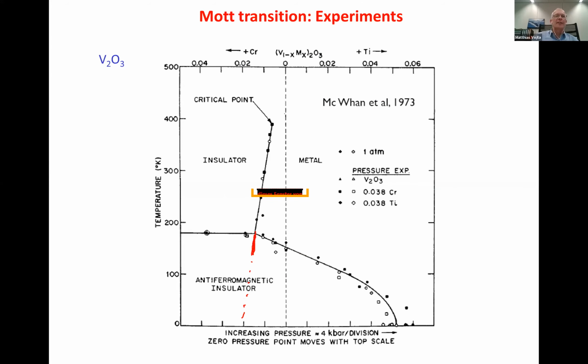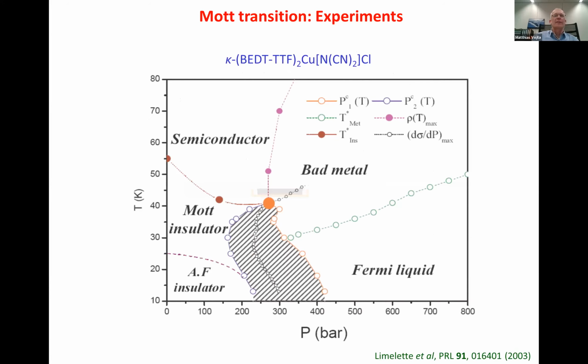Again, for the vanadium oxide, there must be a clear-cut experimental answer, but these data I'm showing are from the 70s, so I'm not sure whether this has been investigated in detail. In these phase diagrams, you actually see that the antiferromagnetic phase is always on the left-hand side of this first order line, so the question doesn't appear in the same way.